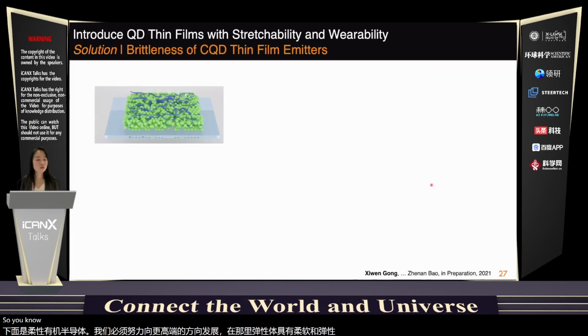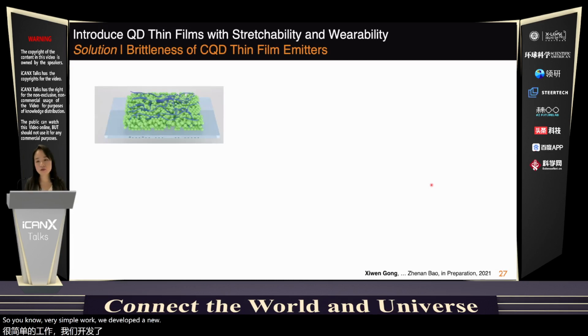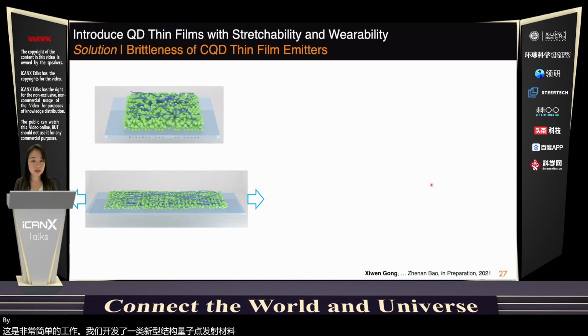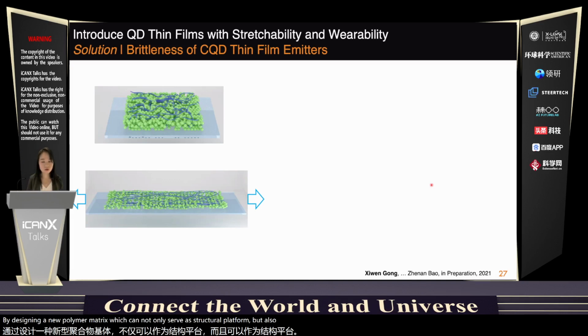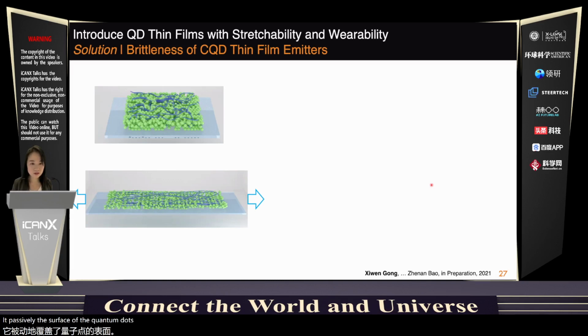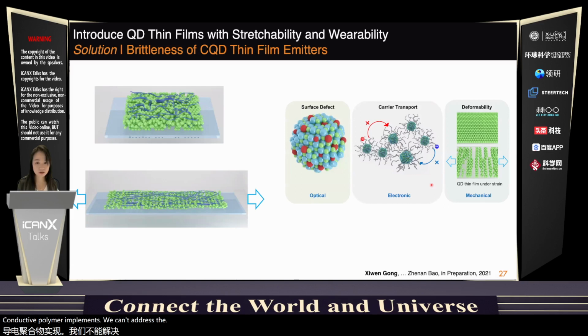So in our very recent work, we developed a new class of stretchable quantum dot emitting material by designing a new polymer matrix, which can not only serve as a stretchable platform, but also optically passivate the surface of the quantum dots and provide electronic transport pathways. Through careful design between stretchable conductive polymer and quantum dots, we can address the three challenges of quantum dots simultaneously.